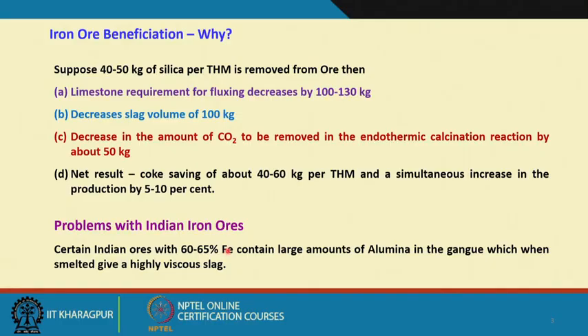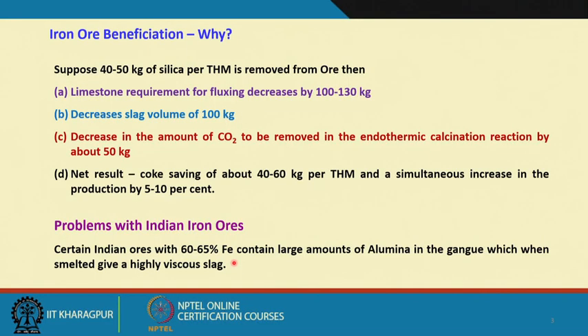So, now this is a good example of the Indian iron ore beneficiation industry. If you look at the problems with Indian iron ores, certain Indian ores with 60 to 65% Fe. Now, when you talk about Fe2O3, what is the meaning of 60 to 65% Fe? I will try to explain fast. If I have a pure hematite, that is Fe2O3, if you do a stoichiometric calculation, you will find that a pure hematite can have only 70% Fe. So, when you have even 60 to 65% Fe in your mined ore, that means it is more than 90% pure.